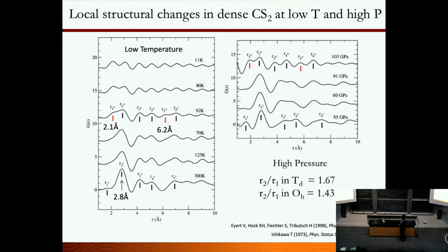And at low temperatures, this is interesting enough, it goes to another phase transition. If you do the X-ray studies at low temperatures, you can see when you lower the temperature from 300 Kelvin to around 40 Kelvin, there's a clear change in the profile. There's a new peak appearing right here. This peak and the ratio between the first nearest neighbor and second nearest neighbors give roughly the ratio of an octahedral structure.